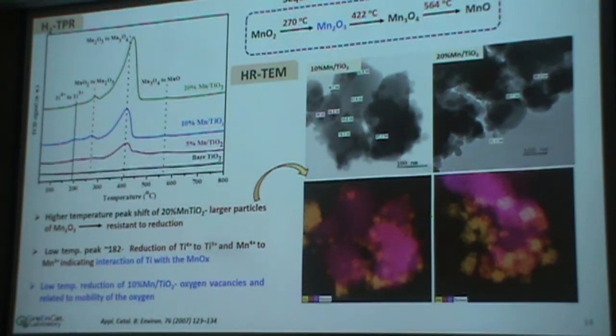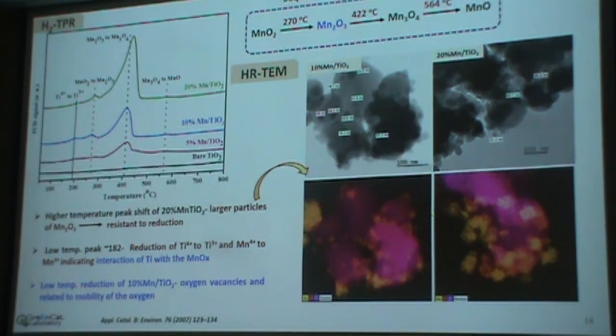And there are three reduction peaks observed, and the main peak is at 422 degrees Celsius, which indicates that the surface is mainly enriched with Mn2O3 species of the catalyst. Whereas as the concentration of Mn increases, the peak intensity increases and the peak shifts slightly towards higher temperature. This mainly indicates increasing particle size of Mn, and larger particles are resistant to reduction. That's why it is shifting to higher temperature. Whereas for oxidation, easily reducible oxide species are required.